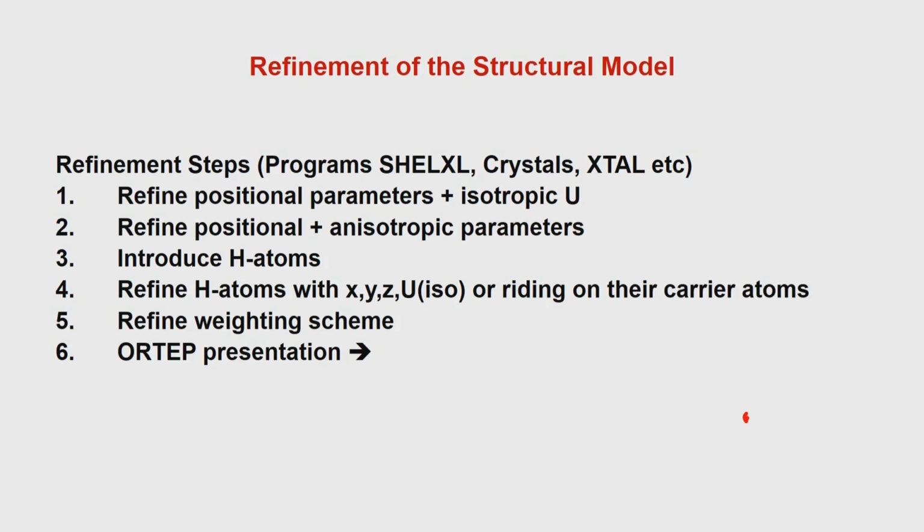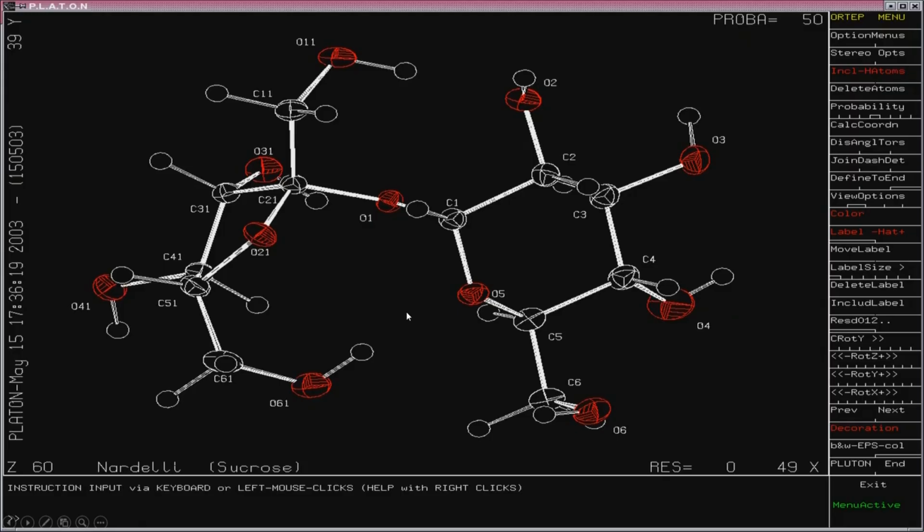The thermal ellipsoid feature will not allow the R factor to go towards 0, because we cannot pinpoint the exact position of xyz. The only thing that will happen is R factors will go lower if you collect the data at lower temperatures. If you collect the data at higher temperatures, then the R factors will not go down. It will have a certain value at which it will remain the same. Such a situation we call convergence. So, we find the optimal value of R, and when we reach the optimal value of R, we say that we have reached convergence in the refinement protocol.